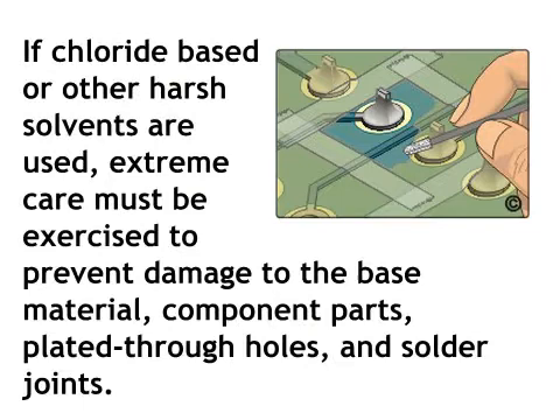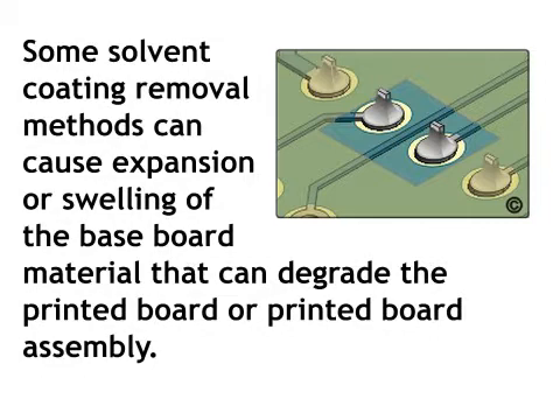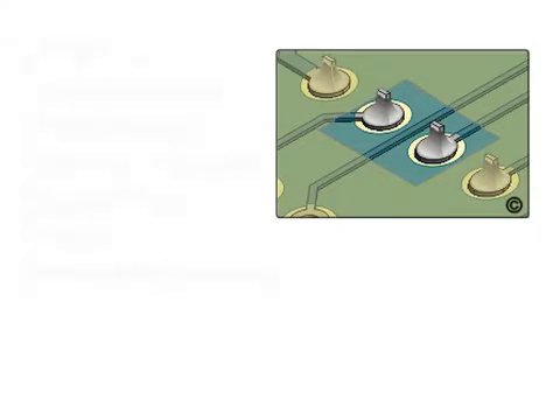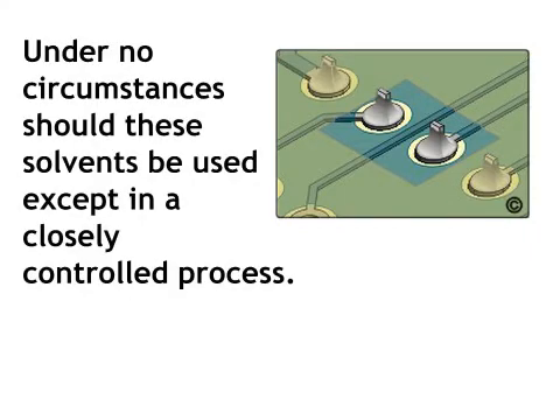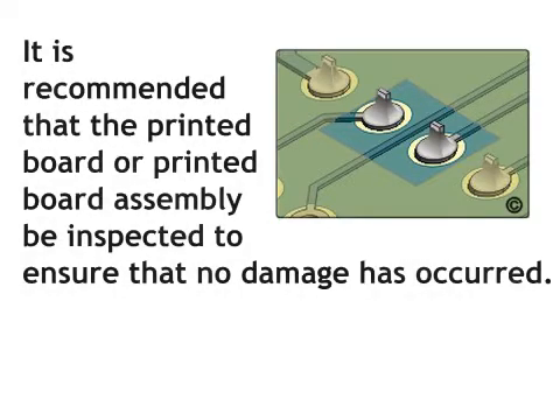If chloride-based or other harsh solvents are used, extreme care must be exercised to prevent damage to the base material, component parts, plated through holes, and solder joints. Some solvent coating removal methods can cause expansion or swelling of the baseboard material that can degrade the printed board or printed board assembly. Under no circumstances should these solvents be used except in a closely controlled process. It is recommended that the printed board or printed board assembly be inspected to ensure that no damage has occurred.